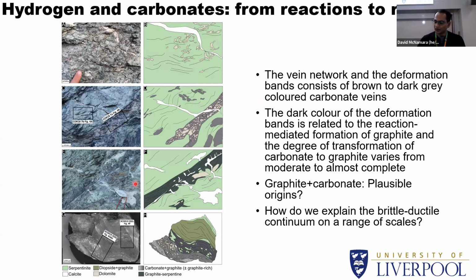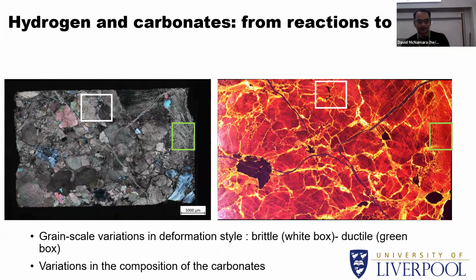single rock. Also, when we looked at some of the specimens, like the bottom panel here, you can see that it has different deformation imprints. You have a part that's fractured, evolving almost into a cataclasite, and then that transitions into a very fine-grained aggregate. So there's almost a brittle-ductile continuum, even on the scale of a hand specimen. It's definitely present in the outcrop, and it's also present on the scale of a thin section.